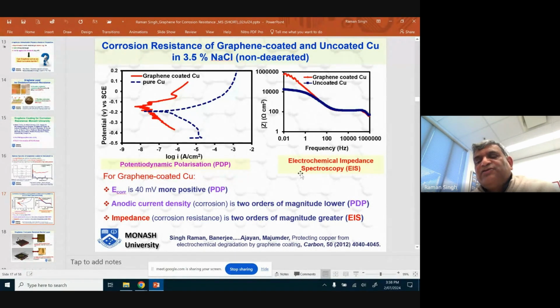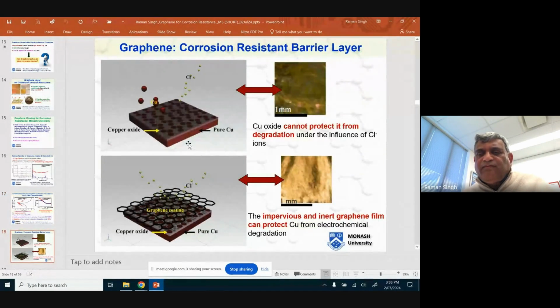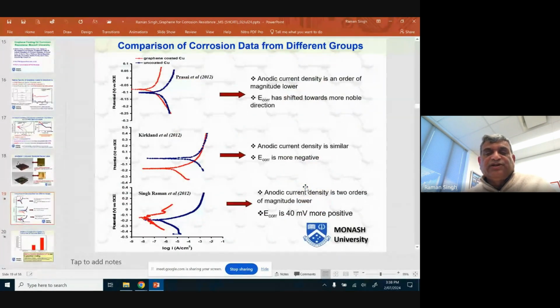And we also did electrochemical impedance spectroscopy, which confirmed what we saw in the potentiodynamic polarization plot. And post corrosion microscopy proved that when you have pure copper, it formed cupric oxide. That's why the dark color, whereas graphene coated copper did not undergo much corrosion.